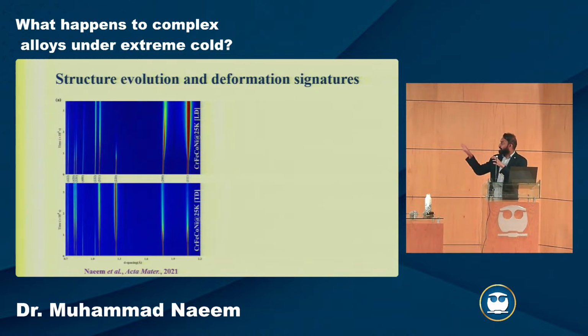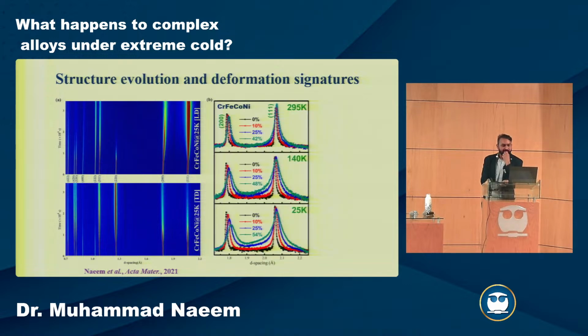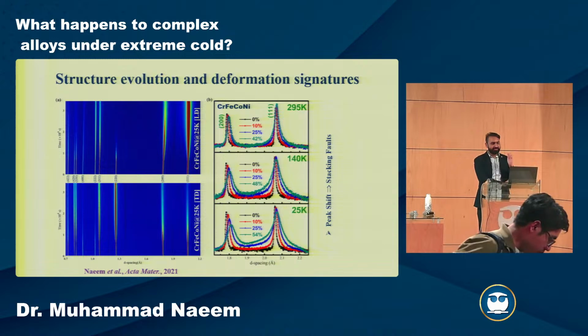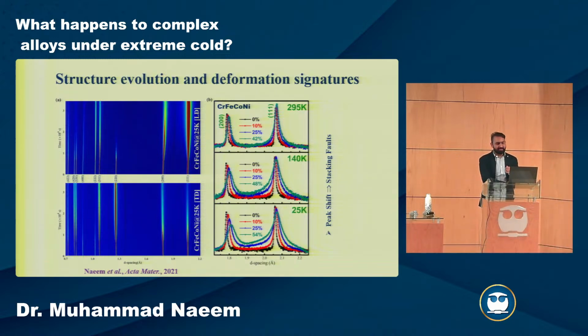So this is the same diffraction peak, but it's shown in 2D, so how they are changing with time. And from this we can see they have deformation signatures, so-called. I put here three temperatures, and you can see at room temperature the peaks are more symmetrical. They become broad at different strain, but not that broad. But when you go to say 25 Kelvin, you see quite asymmetrical broadening, and the peaks are much more broadened than at 295 Kelvin.